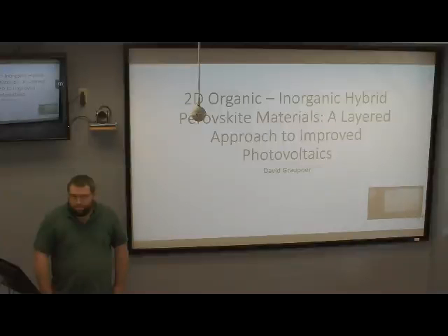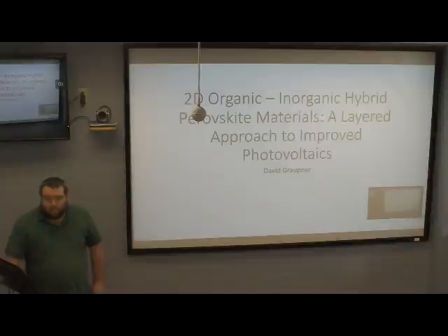So the layered structure does have better stability. Why? The general idea is that the organic ligands that are involved act somewhat hydrophobic for the entire composition of the perovskite layer. And also, what about the surface? Surface volume ratio.